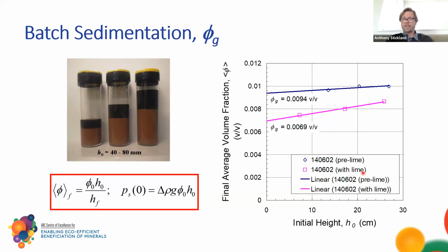This is some tests with a water treatment sludge using ferric chloride to coagulate the material. As you can see, the gel point of this stuff is about 1%. This one's about 0.7%. Very low concentrations of solids.